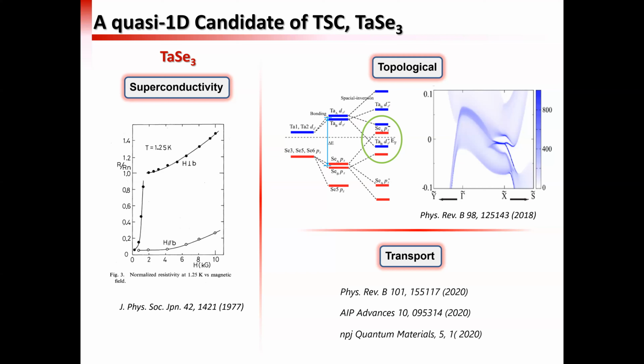Tantalum triselenide has been shown to be a possible superconductor a long time ago. You can see from this transport measurement a sudden resistance drop around 1.25 Kelvin. Of course, it doesn't reach zero, and we think there may be defects in the material, so that the superconducting volume is not large enough. More recently, according to band structure calculation and analysis, this material could be topological, with the selenium p orbital and the tantalum d orbital reversing their order.